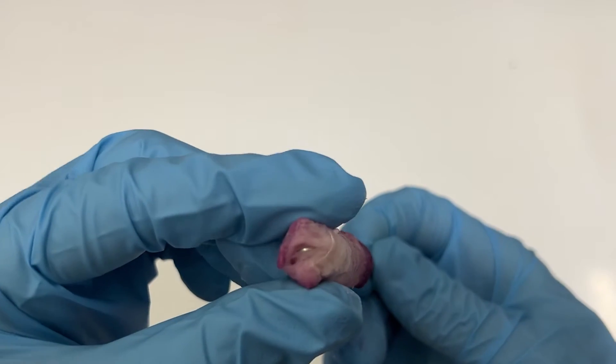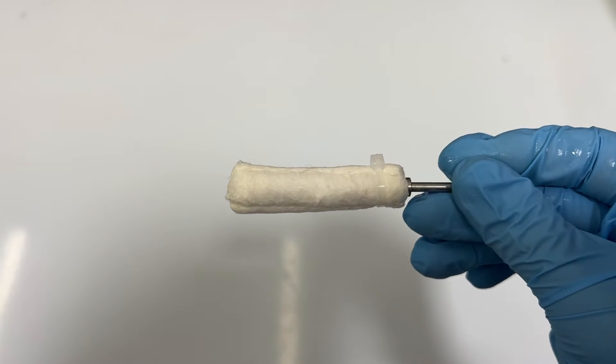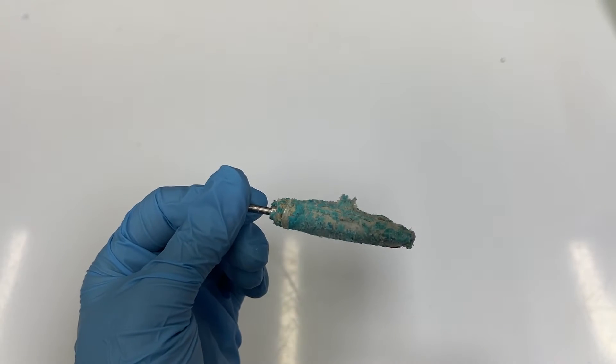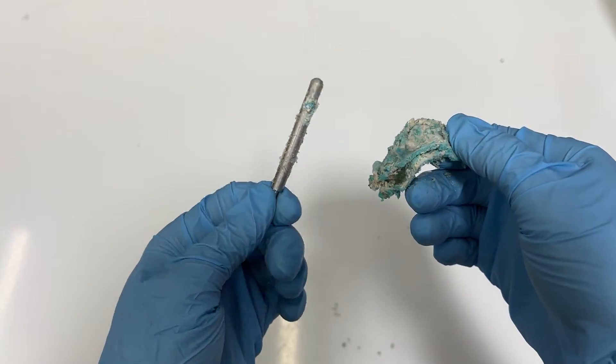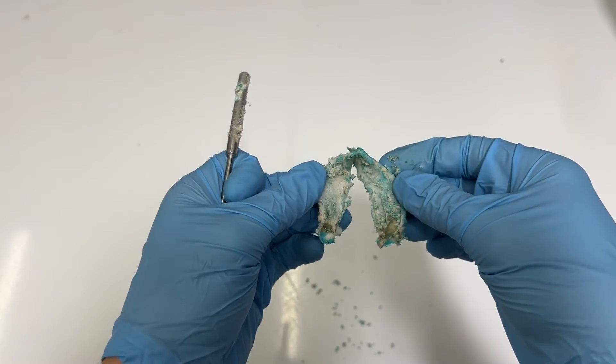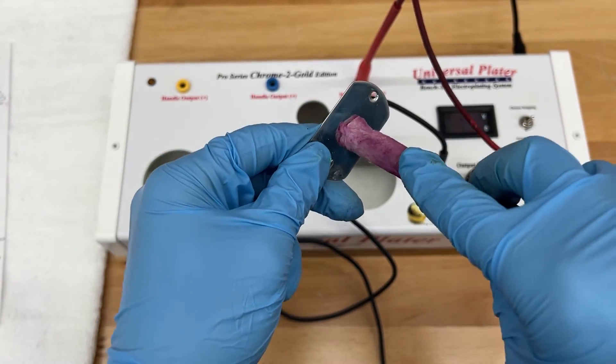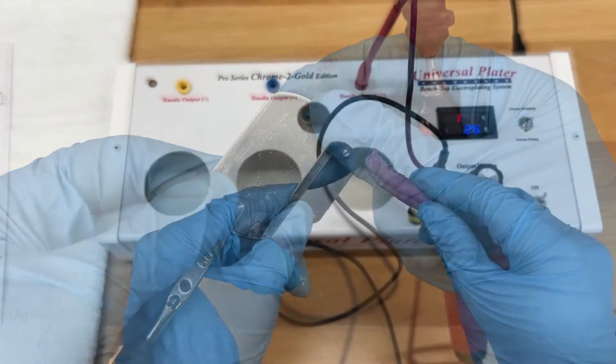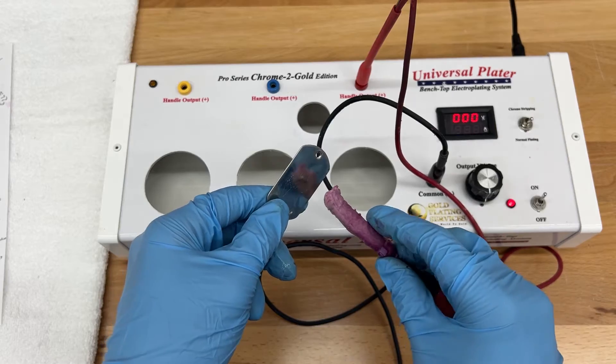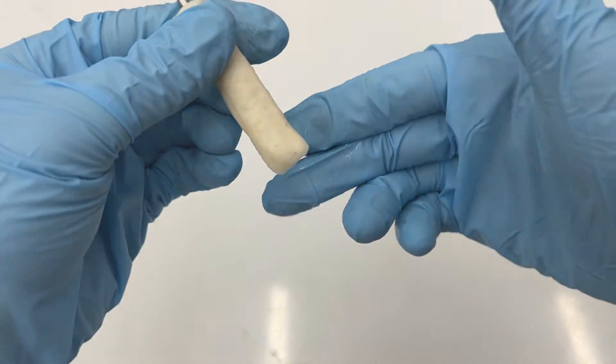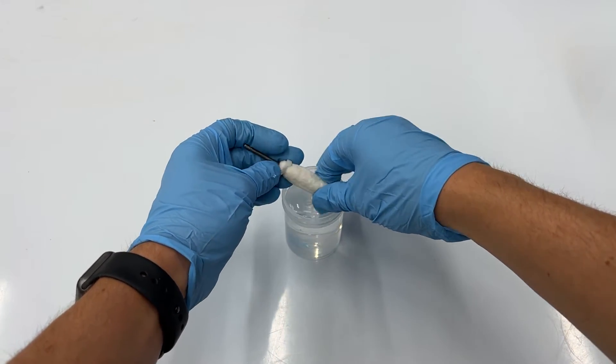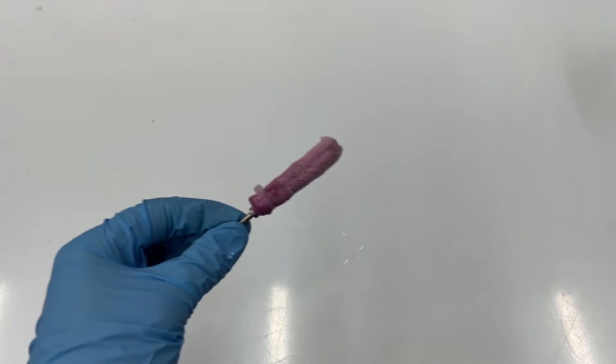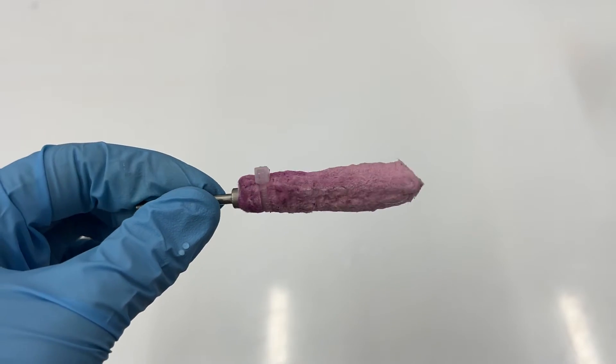Inspect used sleeves to ensure that they are not worn out or exposing the metal bit through the sleeve. If they are, replace them before beginning. Our brush plating sleeves can last for quite a while but they will eventually wear out. Sometimes solutions will cause sleeves to break down quicker such as our activators and our chrome stripper solution. Surfaces that are textured or rough can also cause more wear to the sleeves. Once the sleeve becomes thin enough and the bit is exposed, you run into the risk of scratching the surface that you were plating onto and it will cause the machine to short out when the bare metal anode touches the item you were plating. Thoroughly soaking new unused sleeves is critical. You can leave sleeves soaking in distilled water for an hour or so or even overnight just to be certain. To speed up the process, you can manually massage the material in distilled water to help it absorb faster. Check out this short video for a visual of the process. After new sleeves have become saturated, even after they dry out between uses, they won't have a problem absorbing the solutions again.